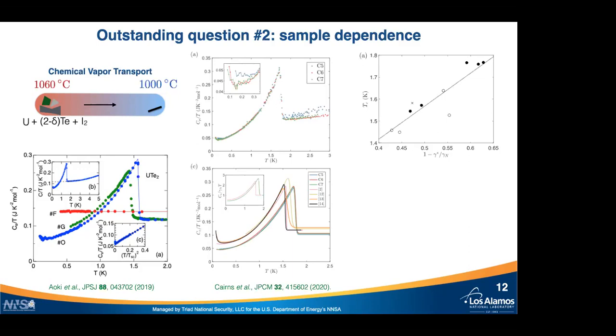So higher TCs are actually inversely proportional. So higher TCs, lower gammas. So in principle, naively, you can think, oh, if I have the cleanest sample possible, TC will be even higher than 1.8 Kelvin, and gamma will go to 0, but that remains to be seen.